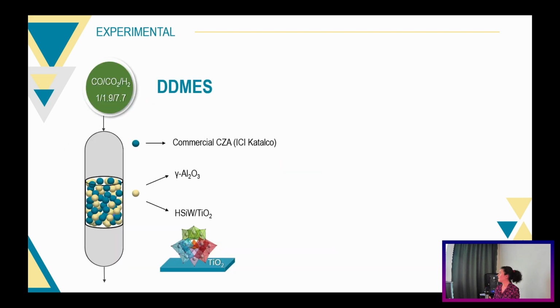So in this work, we have tried to tackle these problems from two different approaches. One of them was to study the effect of the acidic function by comparing two different catalytic beds, consisting of a commercial CZA for the methanol synthesis and, as acidic function, either a gamma alumina or a heteropolyacid based catalyst. In this case, it was a titanium-supported silicotungstic acid, which has already presented very good activity for the methanol dehydration to DME without water deactivation.